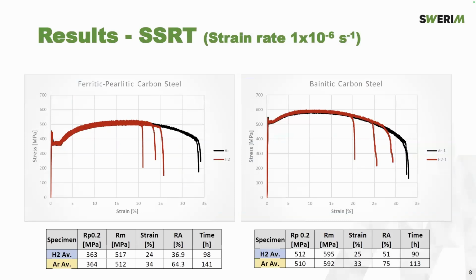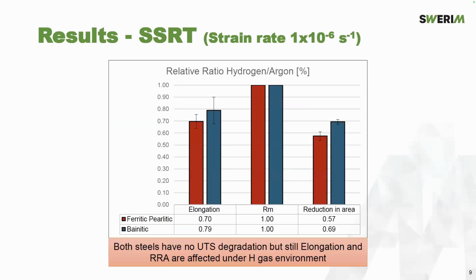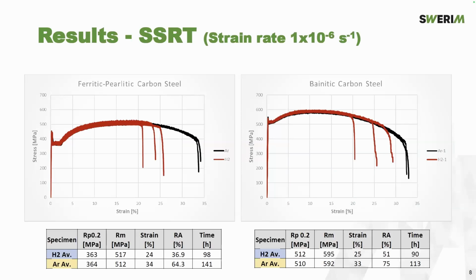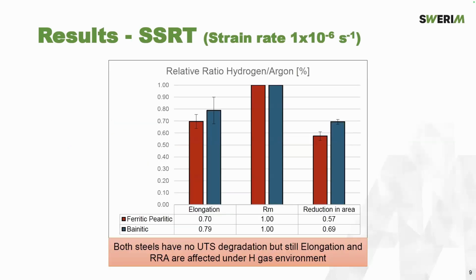So going to the results, we can see that there is more or less the same behavior. We have degradation of elongation on both materials, with a slightly bigger deviation for the bainitic carbon steel. As I told you before, it was a really low strain rate, 10 to the power of -6. So it was a test of 98 hours in hydrogen and 141 hours in argon. And here we can compare both materials. We have some reduction in elongation and reduction in area, and we can see that the bainitic steel behaves a little bit better in this test.